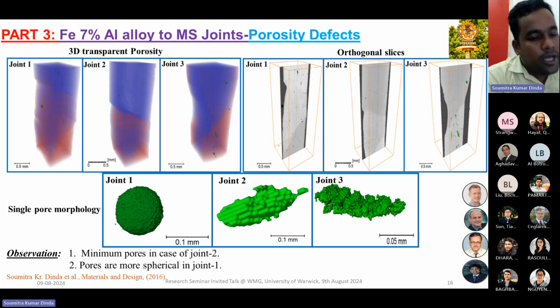And we know that in welding, or any thermomechanical treatment where melting is involved, there are two different reasons for porosity formation. The first is gas entrapment or gas involvement, and the second is contraction pores from the liquid to solid transformation. And gas entrapment pores are spherical in nature because of the lower interfacial energy of the gas.